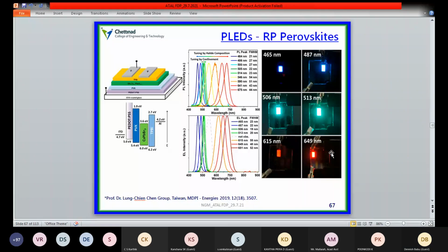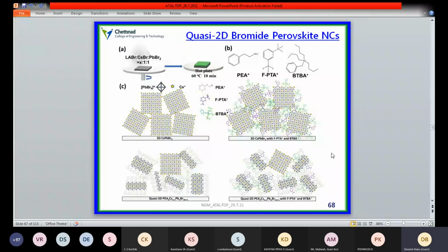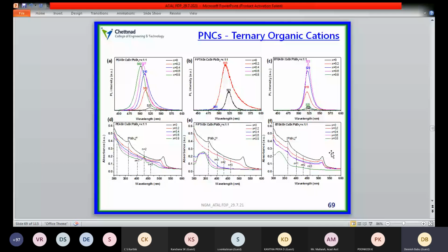perovskite-based LED devices. As I have mentioned, we have also worked on some quasi two-dimensional organic-based perovskite materials. We prepared phenylethyl ammonium and butyl ammonium based perovskites, with different structures. We prepared these using a simple ligand-assisted reprecipitation method. These are their photoluminescence intensities with respect to the green color expected from cesium lead bromide along with the phenylethyl ammonium and butyl ammonium based perovskite systems.